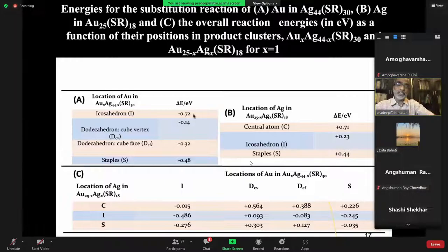But if you do a chemical reaction such that you get this and this, starting from gold 25 and silver 44, you get different kinds of results depending upon where you put the gold and where you put the silver. So let us say in this particular case, silver is put at the central position and gold is put in the icosahedral position. So that way you have created this molecule called Au24Ag1 and Ag43Au1.